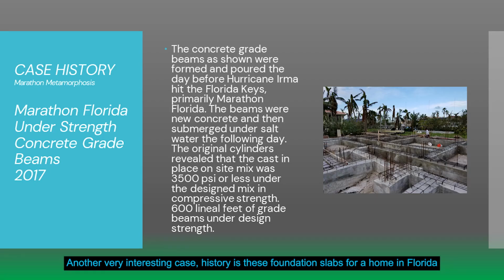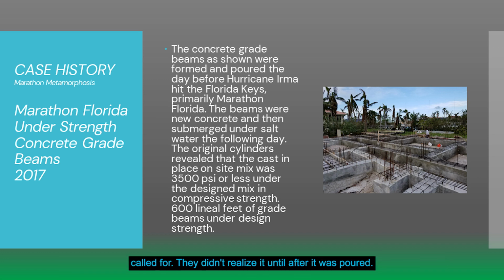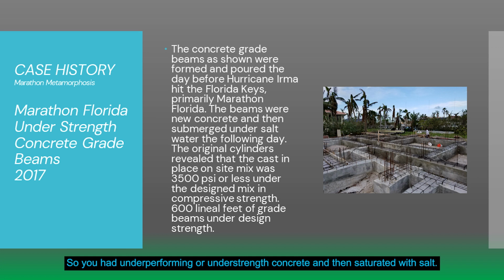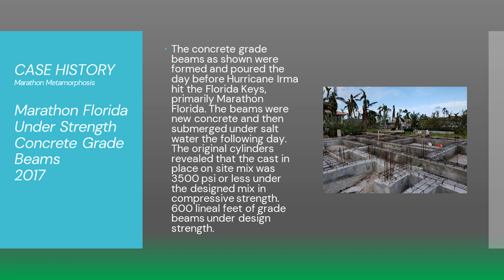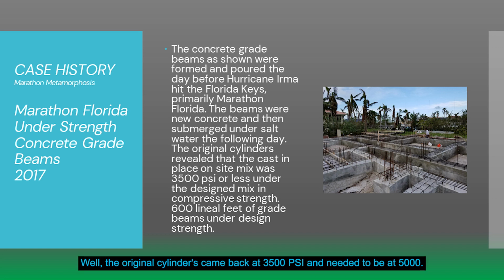Another very interesting case history is these foundation slabs for a home in Florida were poured, and unfortunately the delivery truck brought in 3,500 psi and 5,000 was called for. They didn't realize it till after it was poured. A couple days later, Hurricane Irma blew in and submerged the whole thing in salt water. On top of that, you can see the trees are all shredded. So you had underperforming or understrength concrete and then saturated with salt.